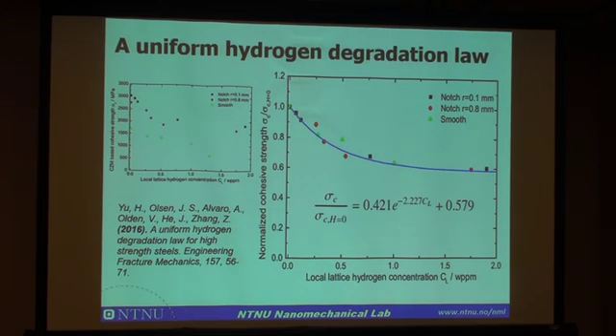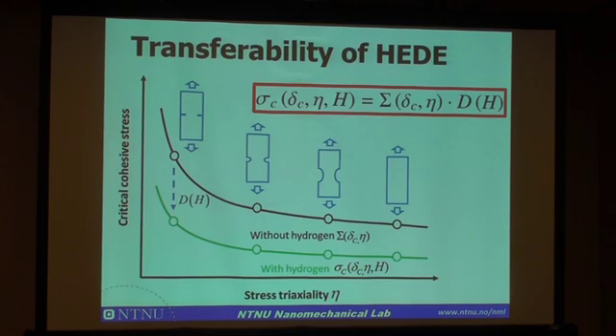So the critical cohesive stress with hydrogen can be expressed as a function of the critical cohesive stress without hydrogen, and a function of local hydrogen concentration. So what we believe for high strength steels, where lattice hydrogen is dominating, we could probably derive such kind of transferability of hydrogen enhanced degradation effect.